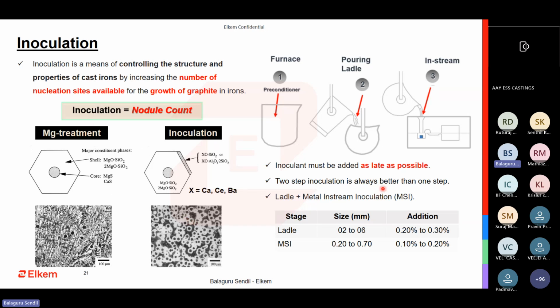So inoculation must be added as late as possible. Two-step inoculation is better than one. If you are able to add MSI, metal stream inoculation, of 0.2 to 0.7, which is the best, and if you're able to add it consistently, then there's no need for multiple stages. One is sufficient. So total inoculation should always be less than 0.4. If you're adding more than 0.4 inoculant after ductile iron treatment, I would seriously reconsider why that is the case.